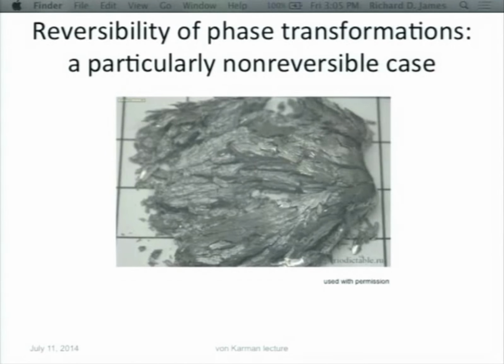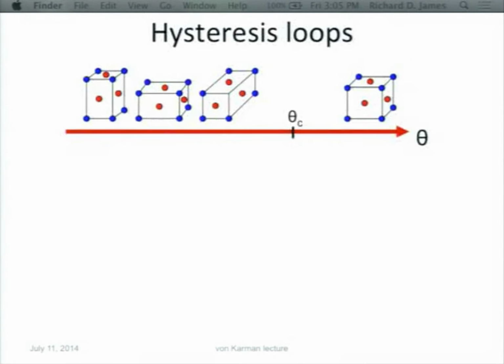People would say that the reason this is not reversible is it has such a big volume change that it tears itself apart. I don't believe that explanation, as you'll see later, but it's the accepted explanation. I could measure reversibility by how many times I can go back and forth through the phase transformation, or I can measure a certain property like the latent heat. Each time I go through the phase transformation, does it give off the same amount of heat and reabsorb the same amount of heat? Any property can be used as a measure of the reversibility of a phase transformation, but I'm going to use a very, very important measure, and that's hysteresis.